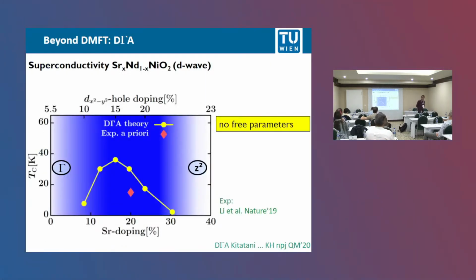Okay, and next we can calculate superconductivity this way. It's the superconducting Tc as a function of strontium doping, and remember we had to translate the doping to the actual filling of our x squared minus y squared orbital, which is shown up here. That is how it looks. In this dark blue regime, we think this one-band description is sufficient. We also have an A pocket, but it's decoupled, and the x squared minus y squared orbital is the correlated one, which we think is responsible for superconductivity. Now here, at low doping, you can have an additional gamma pocket. The physics can be slightly different. Here at large doping, we also get different physics, because then the z squared orbital makes another Fermi surface.